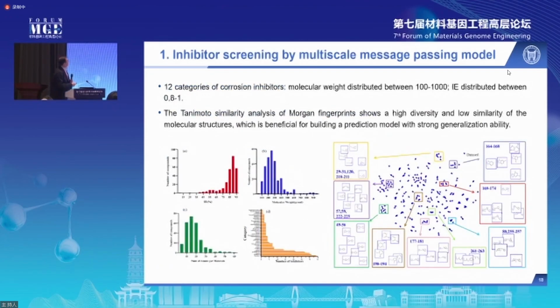And the inhibitors we used consist of 12 different categories, and the molecular weight ranges between 100 and 1,000, which is really a wide range considering these kinds of small organic molecules. And inhibition efficiency covers from 80% to about 100% corrosion inhibition rate.